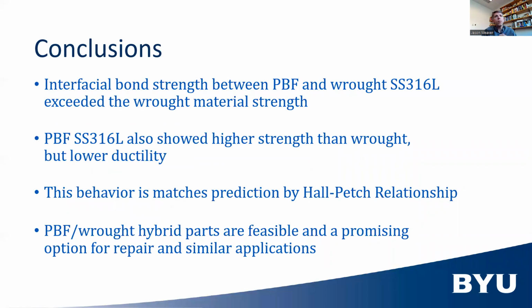So in conclusion, we found that the strength at the interface between the additive manufactured powder bed fusion material and our wrought substrate material exceeded the original strength of the wrought material. And we also saw that the additive material itself was also a higher strength than the wrought material, but lower ductility. We were able to confirm that the Hall-Petch relationship does ring true with our observations. It does a good job of explaining why we saw what we saw.